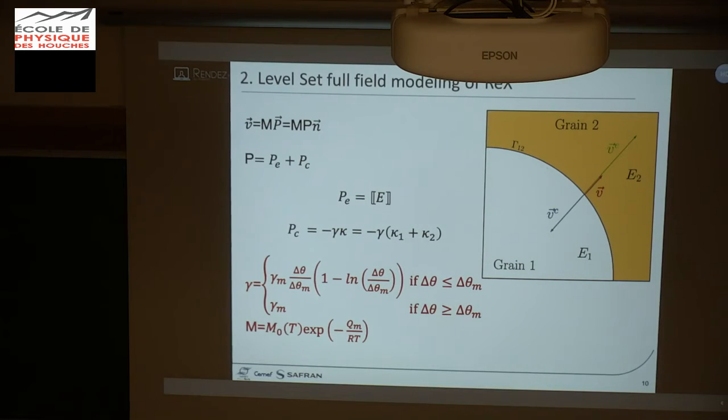Okay, now I explain to you that, compared to classical phase field simulation, in level set simulation all is defined by a kinetic equation at the grain interface, and not by direct minimization of a given energy, but by using a clear kinetic law to simulate the minimization of the system energy. And a very classical law introduced 70 years ago is defined by the equation at the top left of my slide, where you can see a relationship between the velocity of the grain interface, defined as the product of the mobility of the grain interface and the driving pressure of grain boundary migration. And finally, in level set simulation, all the physics is defined by this kinetic equation.